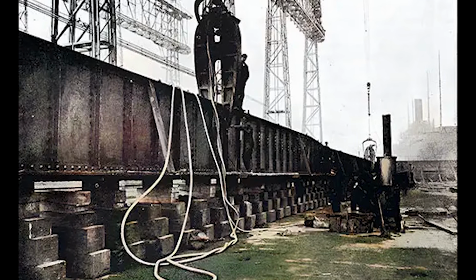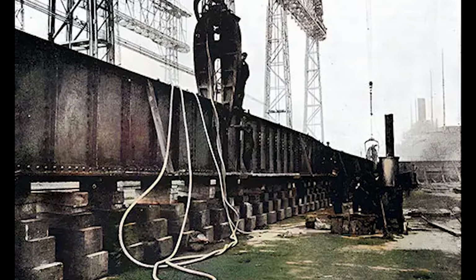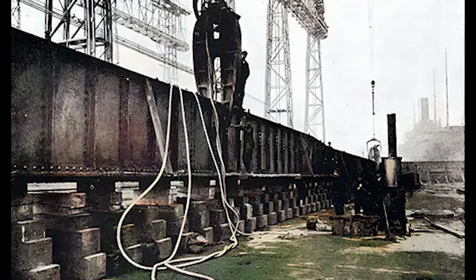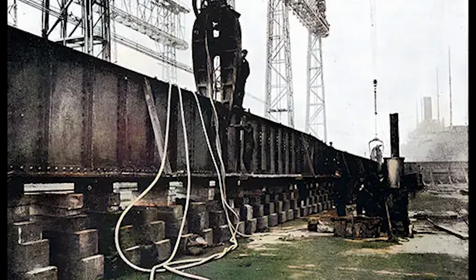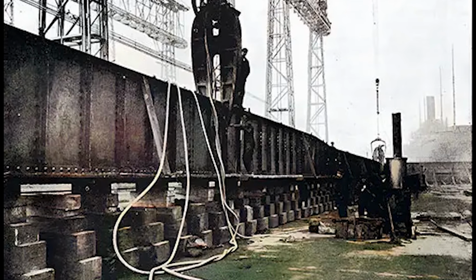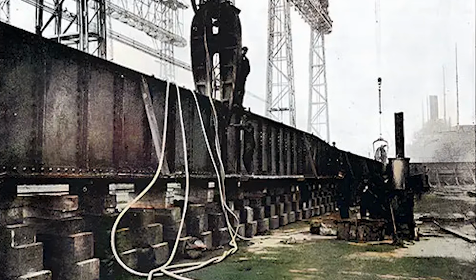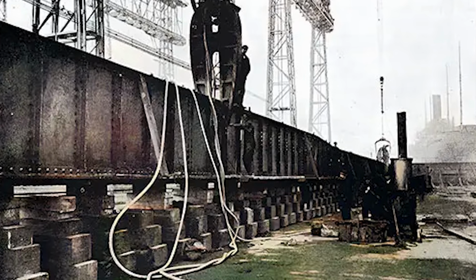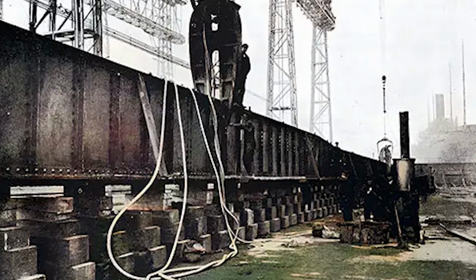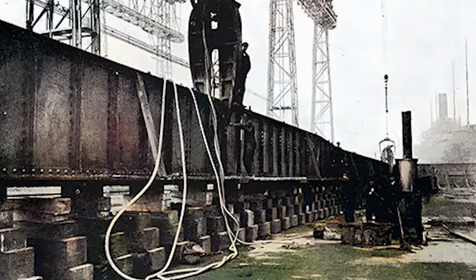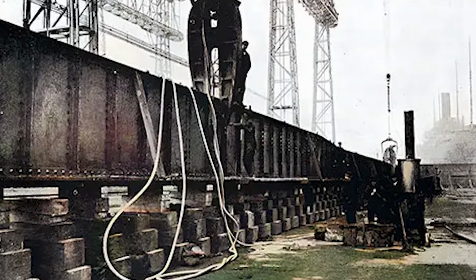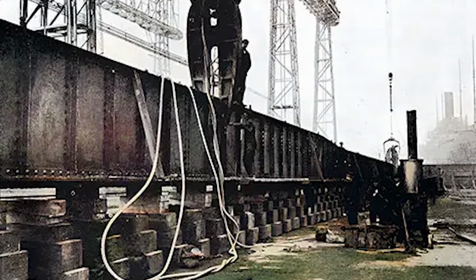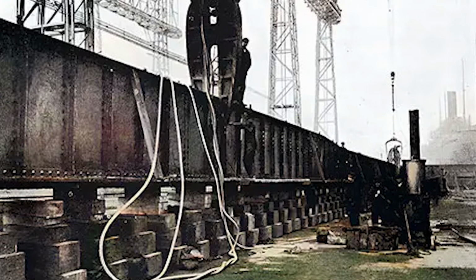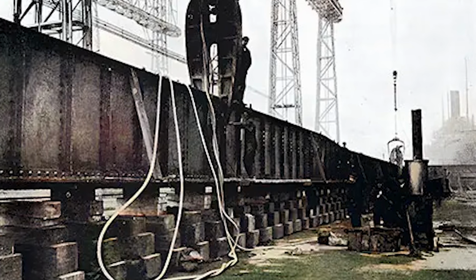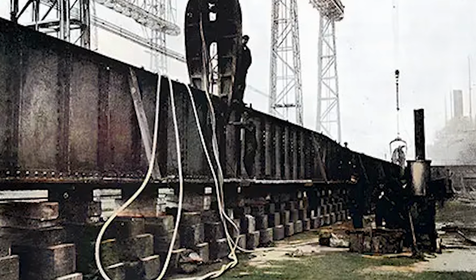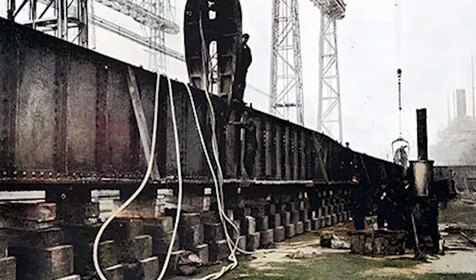The technical mystery deepened as metallurgical analysis revealed that failed steel components showed no evidence of substandard materials or construction defects. Welding quality met or exceeded specifications. Steel composition matched approved formulations. Joint integrity appeared perfect until the moment of catastrophic failure. The steel itself seemed to be changing fundamental properties under specific environmental conditions that remained invisible to conventional engineering analysis. American materials science lacked the theoretical framework to explain why identical steel behaved completely differently in cold versus warm conditions.